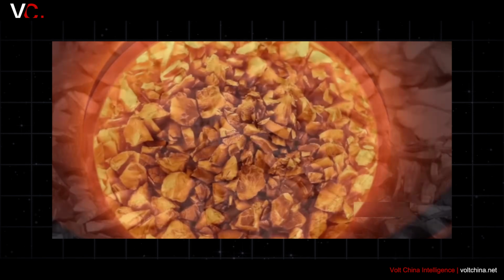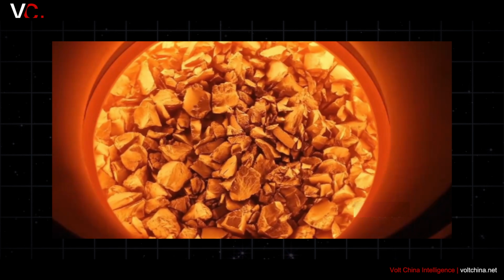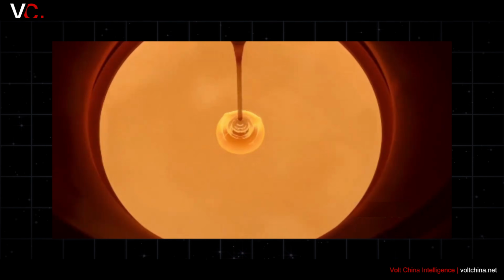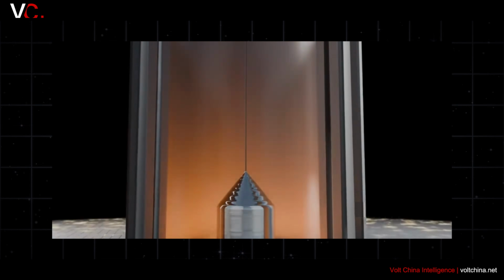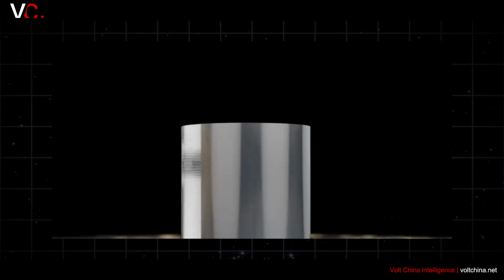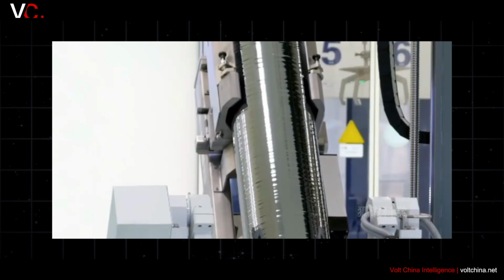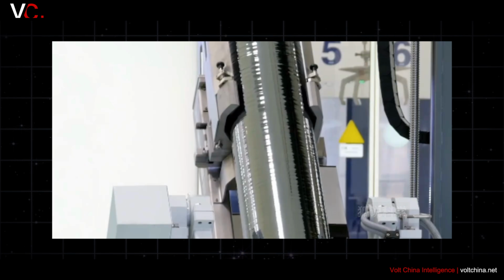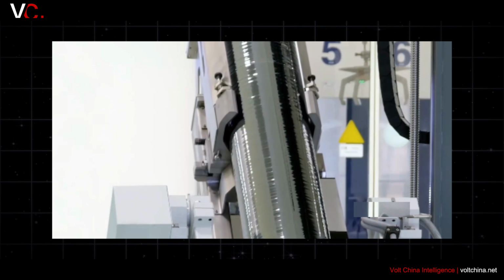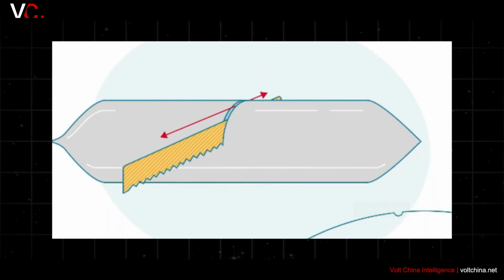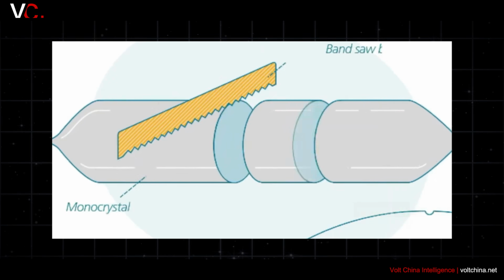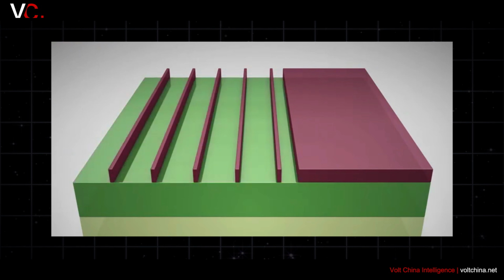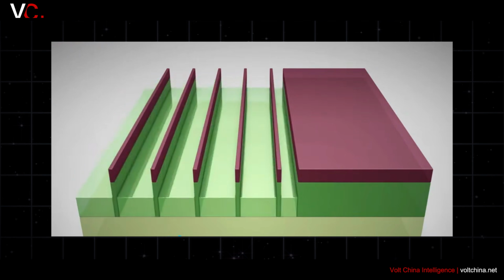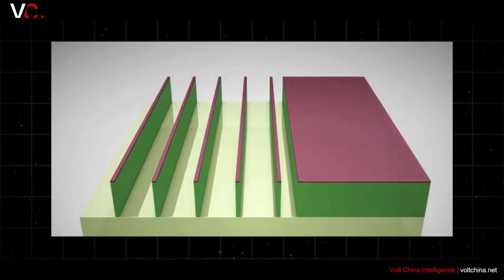Unlike standard silicon, which is simply melted and pulled, silicon carbide must be grown from a vapor at over 2000 degrees Celsius in a sealed graphite crucible. You cannot see inside. If the temperature fluctuates by even a fraction of a degree, or if the thermal stress distribution is uneven, microscopic crystal defects multiply. By the time you slice the crystal into wafers, it shatters. This is why the yield rate is the ultimate arbiter of survival.